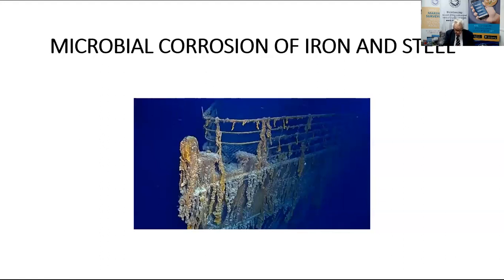There are four groups mentioned, however, and the most important group associated with the corrosion of ferrous metals are those in whose metabolism sulfur and or its compounds plays an important part. Remember what I said about the sulfur in the Titanic steel. Pitting from microbiological sources has a high surface area depth ratio. The sides of the pits are stepped and the bottom of the pit is flat. Sulfate-reducing microbes leave the bottom of the pit coated with a soft black substance, easily cut with a penknife and giving off the characteristic bad egg smell of hydrogen sulfide.